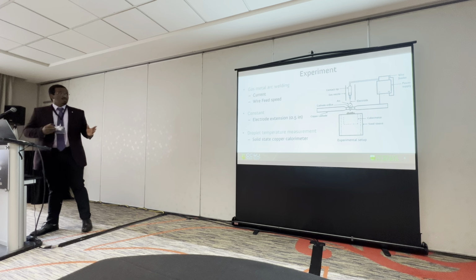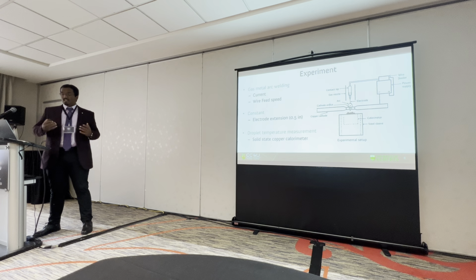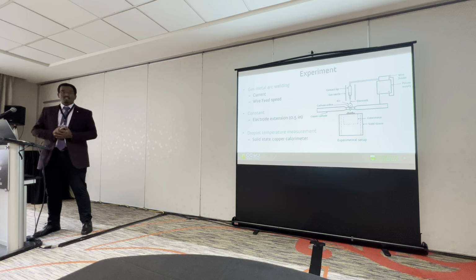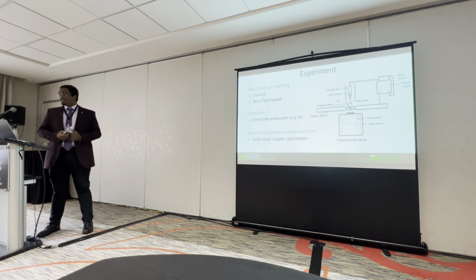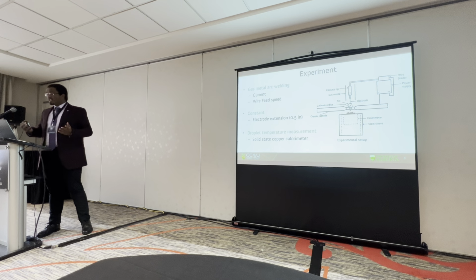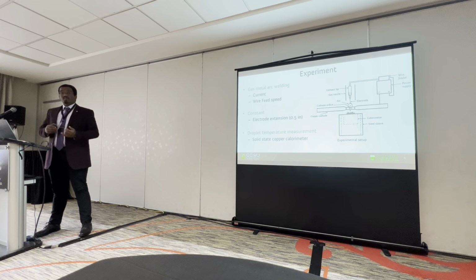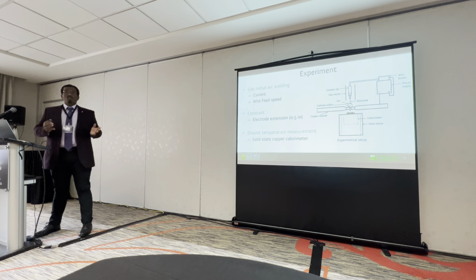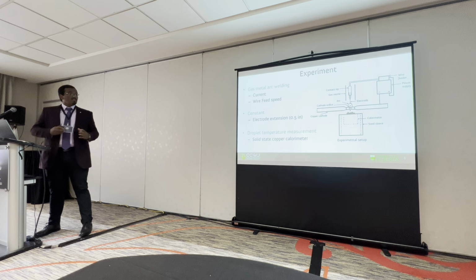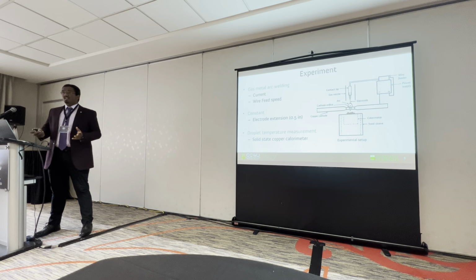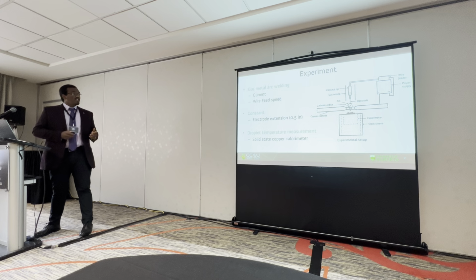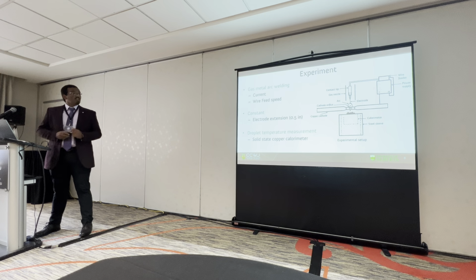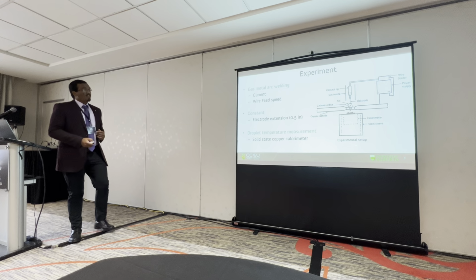For the experiment, some of these have already been spoken about in the past presentation, but I would still like to give it a good depth. We use gas metal arc welding for the process, in which we obtain the current, the wire feed speed, and also the droplet temperature. We have a constant electrode extension for all the experiments, which is 0.5 inches. For our droplet temperature measurement, we use a solid state copper calorimeter, and here is the setup which was used.